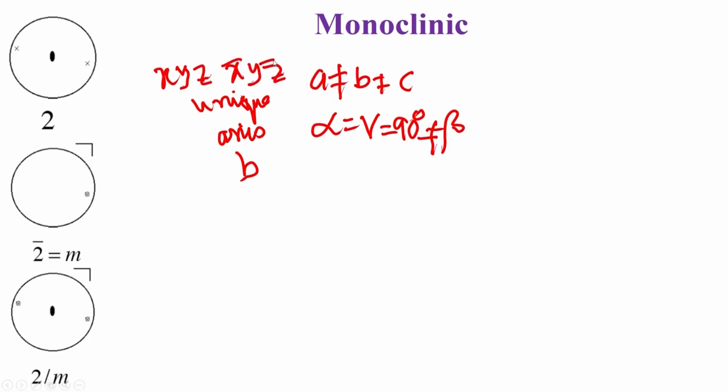So, obviously, the number of objects which can come in this particular crystal system, monoclinic with a two-fold point group symmetry, will be Z equals 2 in the unit cell. So, there are two molecules in the unit cell, and these two molecules are related to each other by x, y, z and x bar, y, z bar. Needless to say, it is not necessary that we have to have one cluster like what we show here. We can have more than one cluster. I will just explain that in a second.